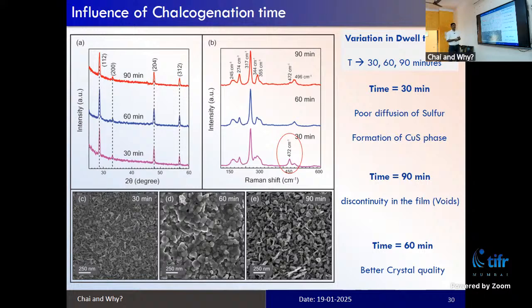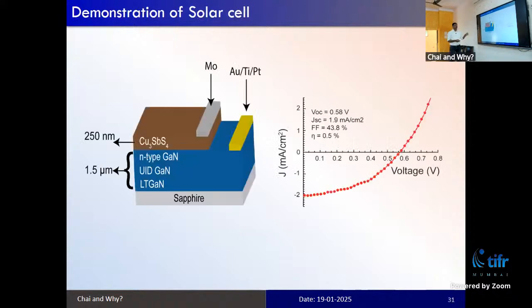After getting the phase pure material, we have demonstrated a solar cell. In this, we have used copper antimony sulfide as a material system, which is intrinsically a p-type material, and we have used n-type gallium nitride. The gallium nitride is grown using a MOCVD reactor, and then we measured the efficiency of the solar cell. The efficiency is something around 0.5%, which is very low as a starting material.